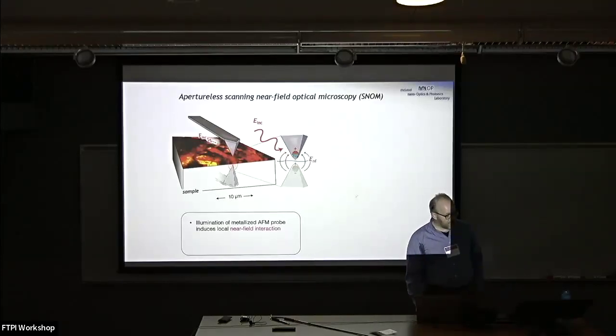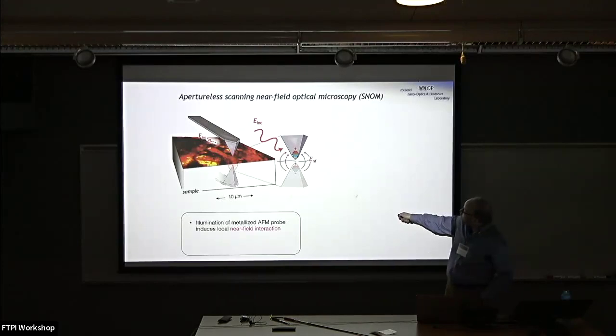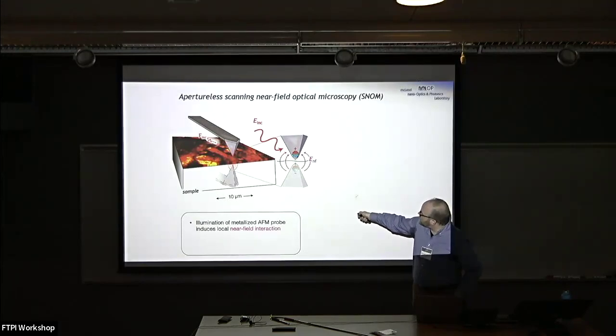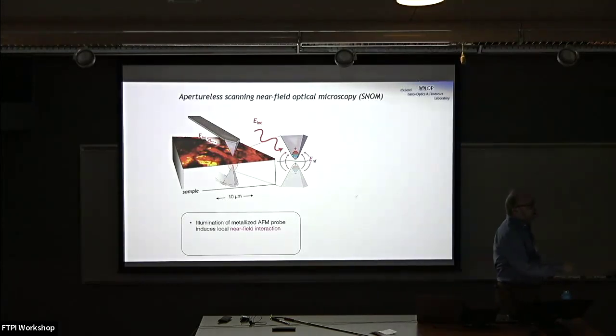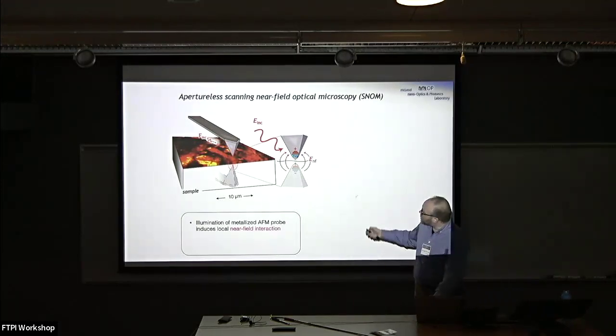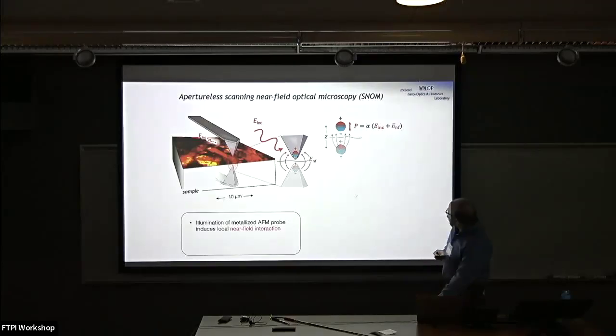And if we do a little zoom in here, we see that our probe polarizes in response to light. And as well, if we bring that probe close to the surface of the material that we're interested in imaging, then that material will polarize in response to the dipolar probe that's right above it. And now we have two dipoles. We're going to have strong electrostatic near fields between these two dipoles. So our real probe is interacting with its own image in the sample.